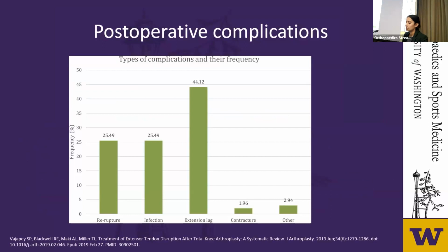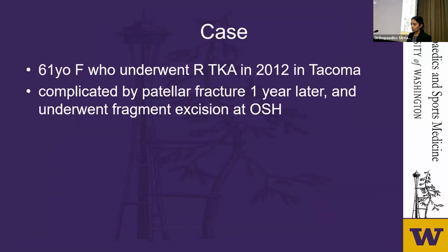And the most common complications after repair or reconstruction of the extensor mechanism, as reported in a recent systematic review in the Journal of Arthroplasty, was extension lag of 30 degrees or greater, at 45%. And the rates of re-rupture and infection were also similar, around 25%, and contracture was less common at 2%. So we'll move on to our case.